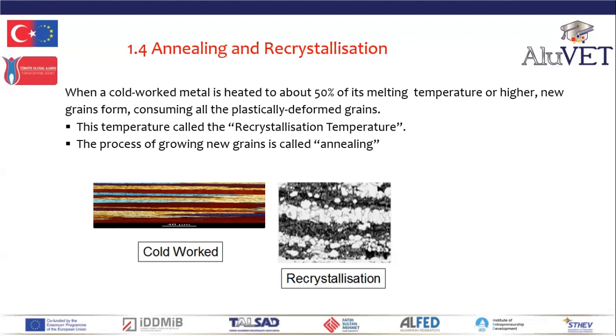Now, when we cold work a metal, we deform the grains, we put a lot of force, a lot of stress and energy in, and cold working traps some of the energy of cold work within the deformed grains. When we anneal, we grow new grains. So annealing is a function of the degree of cold work. Remember, we have trapped the energy of cold work within the grains. So the greater the amount of energy trapped, the greater the amount of cold working of those grains, the quicker and the easier the grains will anneal.